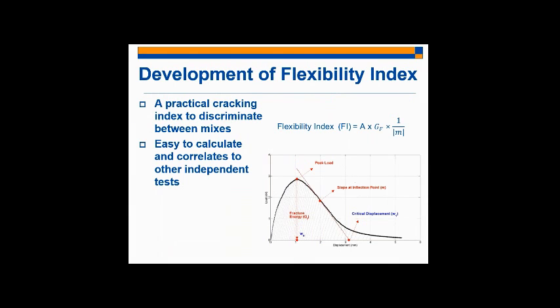And so moving on to the developed flexibility index, what we basically did is we took a step back and we looked at the critical parameters that I discussed earlier, and we said, how can we characterize different materials, and how can we distinguish between different materials? And the result that we came up with was purely geometrical. We found the answer to be in the geometrical properties of the load displacement curve. So the fracture energy is, again, just a geometrical characteristic of the load displacement curve.